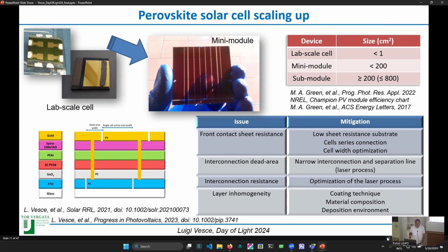That's why when I need a big substrate, I don't fabricate just one cell, to face this issue of the front contact sheet resistance. Then you have the issue related to the interconnection dead area, which we already discussed. So here we have to narrow the interconnection and separation lines. So it's a matter of optimization of the laser process, and the layer inhomogeneity that is related to the deposition of each layer. Maybe it can be simple to deposit on a very small substrate, but it can be completely different when you are going to deposit on a very big substrate. Here you have to work on the coating technique, material composition, and the deposition environment.